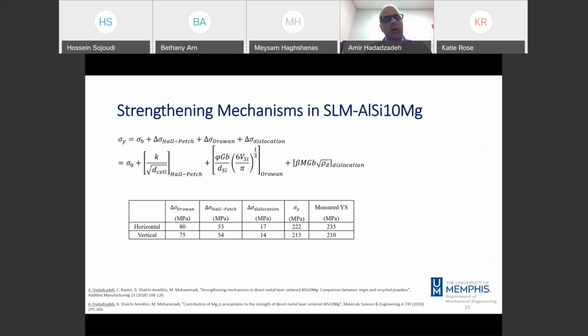Considering these effects, we can use the fundamentals of alloy hardening to study the strength of the material. So as I mentioned, the eutectic silicon walls are acting as barriers against the dislocation motion. So they act like grain boundaries. So their role is similar to the Hall-Petch effect. We have silicon precipitates. They can act as an Orowan strengthening mechanism, and we have the pre-existing dislocation network. So we have dislocation hardening as well, because in presence of other dislocations, there is an interaction, in most cases, a repulsive interaction between dislocations. So we have more hardening in the material.